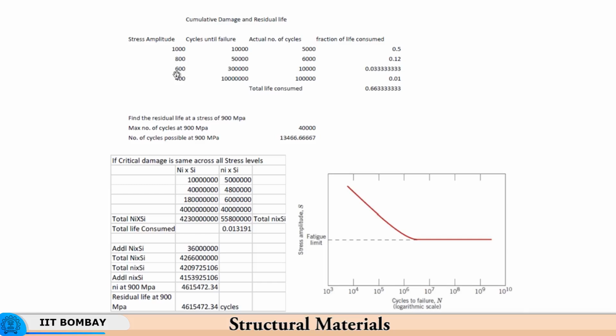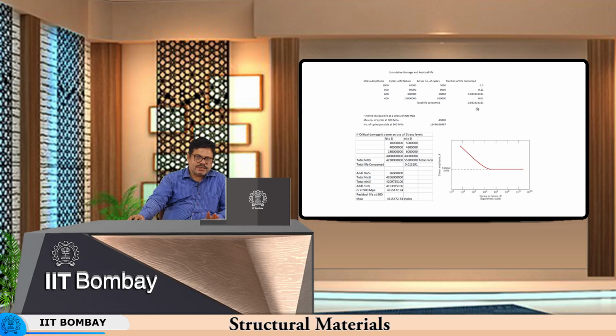I have 600 MPa and 10,000 cycles, and the damage that has been introduced by this is quite insignificant at just 3.33%, and therefore, a very small amount of damage. And if you look at 400 MPa, which is much less than 600, the damage is even less at just 1%. So, effectively what I find is that over these cycles at these 4 different stresses, I have consumed 66.33% of the life. So, the total damage that has accumulated is 66.33%, which means that the available life is 33.7% roughly.